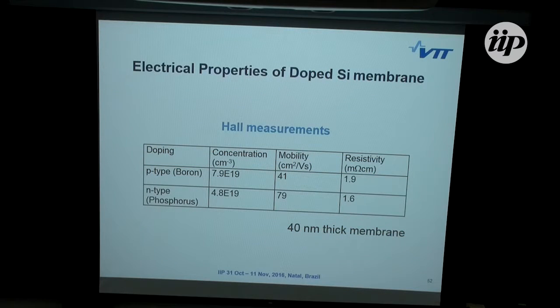And this is our first set of samples which we got. This is a 40 nanometer thick membrane. From Hall measurements, we have P-type at 8 times 10 to 19 carrier concentration, and N-type, phosphorus, at 5 times 10 to 19. So the resistivities are below 2 milliohm centimeter, which was close to what we aimed. These were a little bit lower than we expected, but anyway.